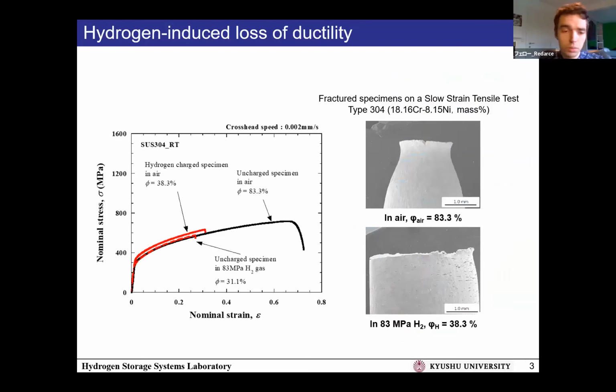So what is hydrogen embrittlement? There's mainly two big impacts. The first one is a loss of ductility of materials. Here a slow strain tensile test was performed, and we can see there's a big difference between a test made in a normal air environment, like around us now, and one in 83 megapascal hydrogen environment. There is a big difference in the shape of the part where it broke, and it's due to the loss of ductility implied by this hydrogen embrittlement.